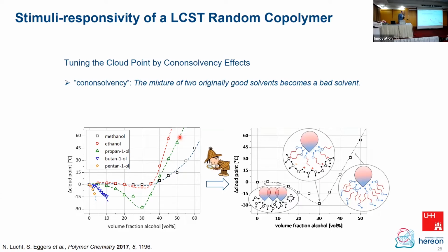And this polymer still caused some trouble and was interesting. I show you a few things here. This is a plot where we added different alcohols to our water, so the water is now contaminated, if you like, with different alcohols. What is plotted on the y-axis is the delta cloud point temperature, meaning the deviation from the cloud point of the polymer in pure water. And what you see is that for certain alcohols, you get an immediate drop of the cloud point, meaning that adding alcohol is not good for the solubility of the polymer.